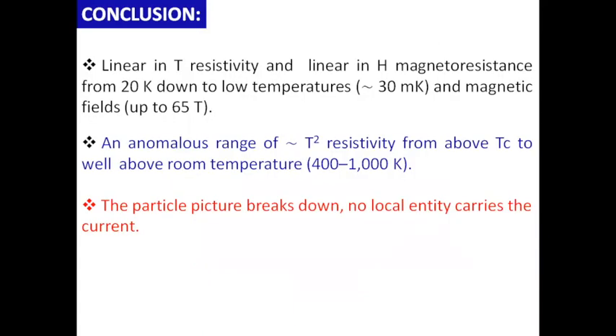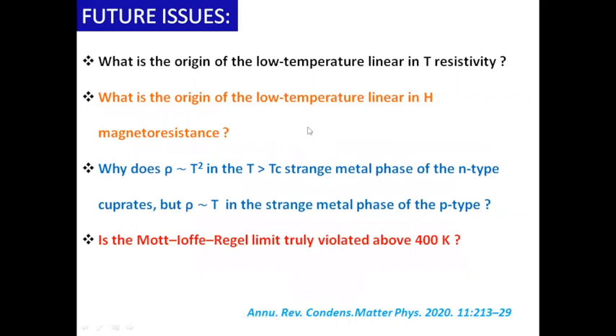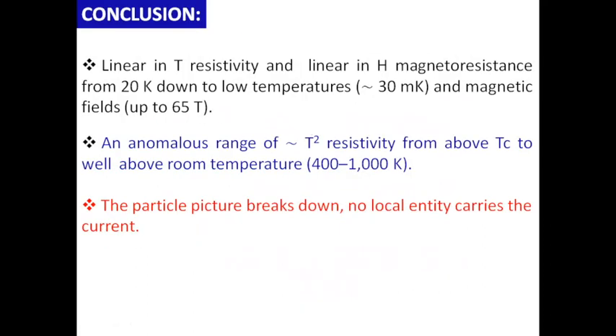Now, what we have found here is that the concept of the quasi-particle is no more, here with the T-linear resistivity. A very similar kind of feature has also been observed in magnetoresistance, the measurement of resistivity as a function of temperature in the presence of a magnetic field, from 20 Kelvin down to the millikelvin range. And you see the magnetic field up to 65 Tesla.